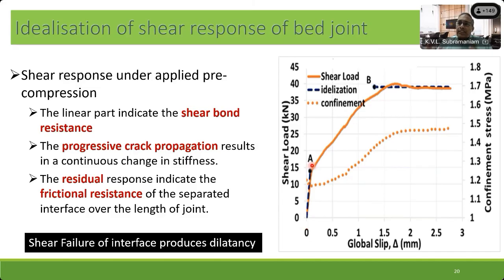This is because the shear interface is getting engaged. The bond between the two materials is getting engaged, and a larger and larger amount of shear force, or stress, can be transferred across these two bricks up until a certain point when you see a sudden change in the slope. Now, with the change in the slope, the confinement starts to increase. So what's happening here?